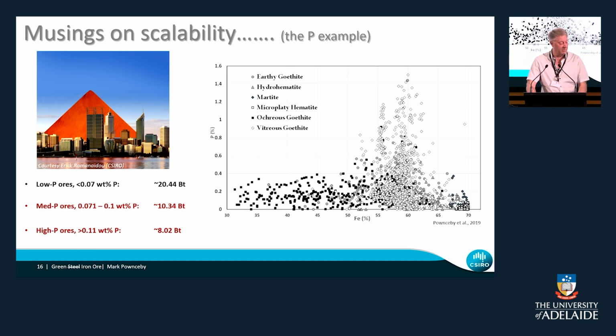If you look down in the bottom left, the spec for phosphorus from steel mills is around about 0.07 weight% phosphorus in an ore. And if you look in Western Australia, we've got at least 10 billion tonnes of ore that's 0.07 to 0.1% phosphorus. And we've got another about 8 billion tonnes that are greater than that. So we've got 18 billion tonnes that are out of spec. And we've got to process that. And we've got to beneficiate that. And we've got to remove those impurities.